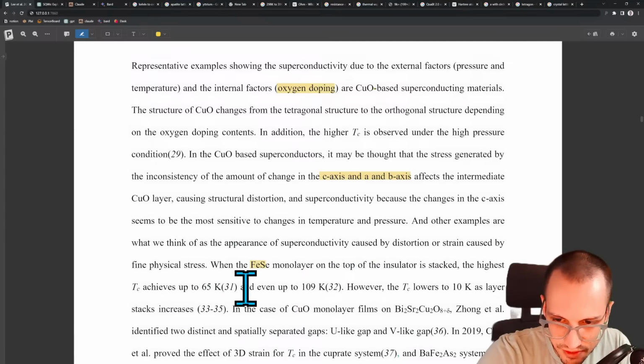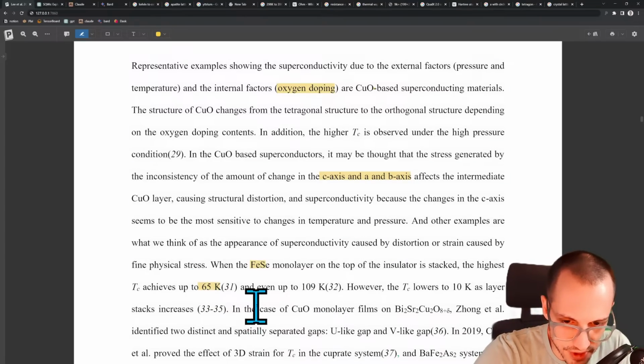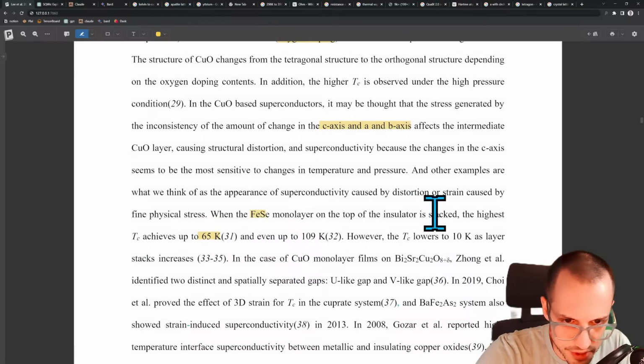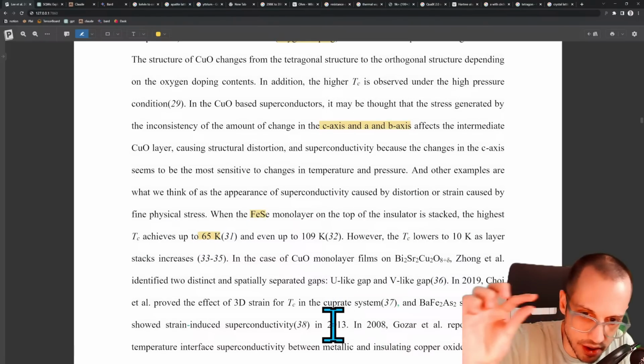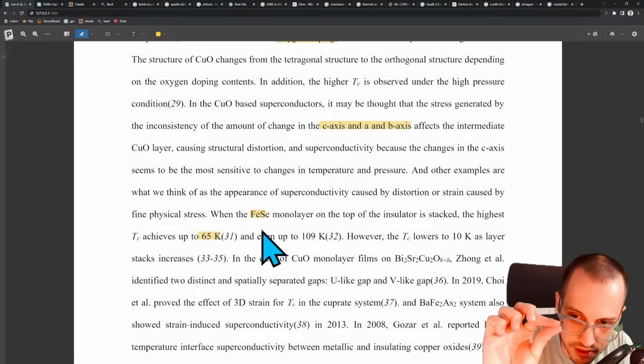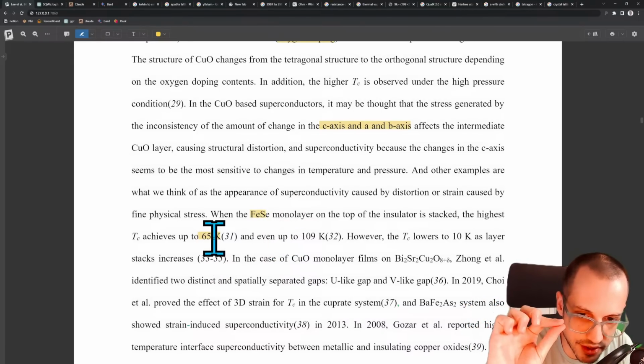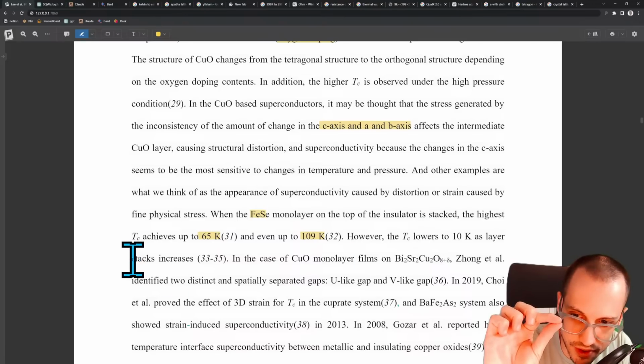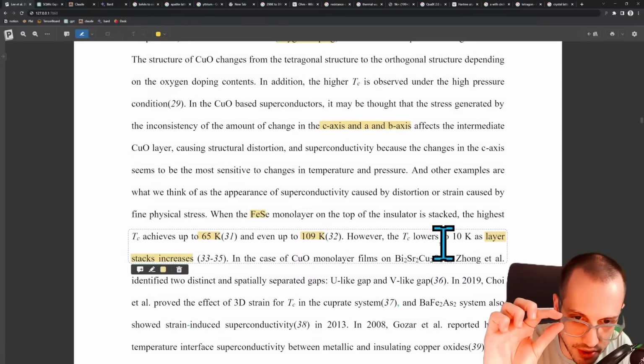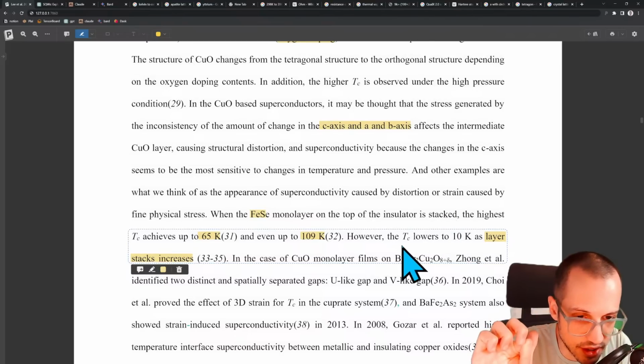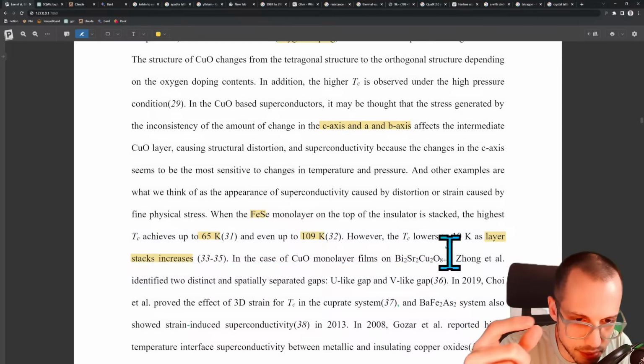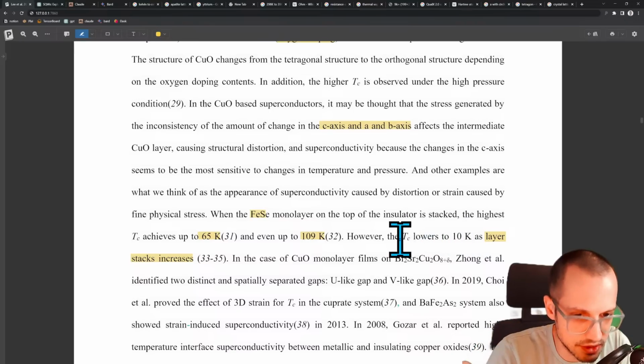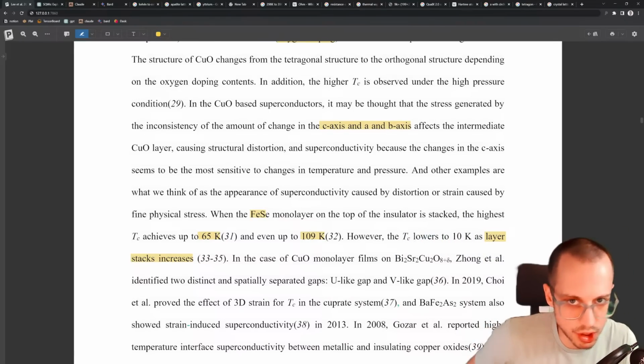The highest critical temperature is 65 Kelvin, which is actually very low. So 65 Kelvin, 0 Kelvin is basically absolute zero. So 65 Kelvin is extremely low temperature, even up to 109 Kelvin. However, the critical temperature drops to 10 K as layer stacks increases. Okay, so this makes sense. So if you have a very thin sheet of this Fe metal, you can get superconductivity at a slightly higher temperature. But as soon as you have more and more layers of this metal, then your critical temperature is going to get lower and lower, which is consistent, right? It would make sense that if you have a very thick piece of metal, the critical temperature is going to be very close to absolute zero, which is why this superconductivity has been such a hard problem to solve.